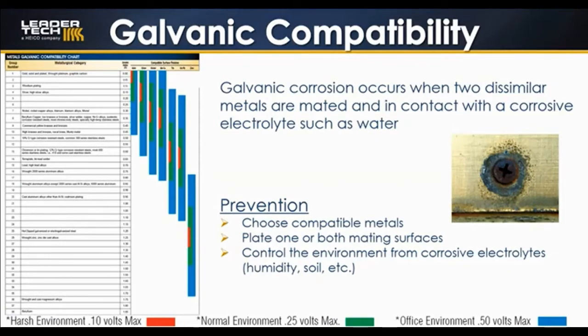For harsh environments like outdoors or high humidity, it is recommended that the difference between the metals not be more than 0.1 volts maximum. For example, nickel is 0.3 volts and beryllium copper is 0.35 volts. Their difference is 0.05. These metals are very compatible. For normal conditions, we recommend a max difference of 0.25 volts. This would be something like a warehouse that is not temperature or humidity controlled. And for controlled environments, we recommend a difference of 0.5 volts max. The best prevention for galvanic corrosion protection between the enclosure shielding gasket and mating surface is to choose compatible metals, plating on one or both of the mating surfaces, and controlling the environment from things like humidity or soil.